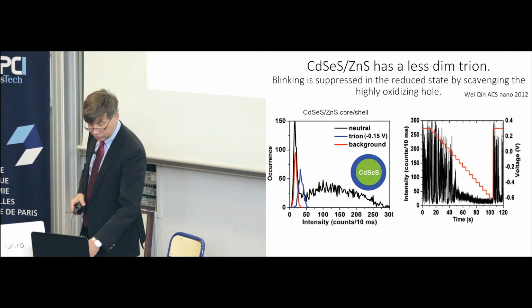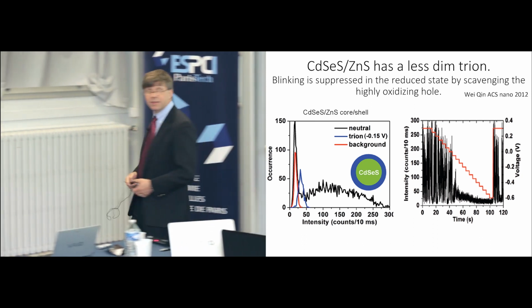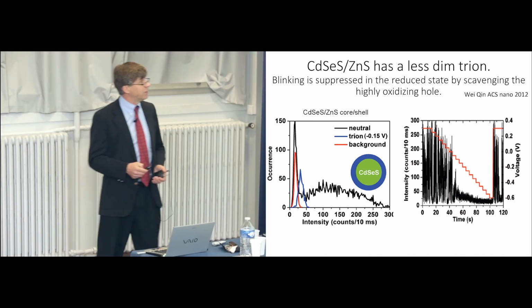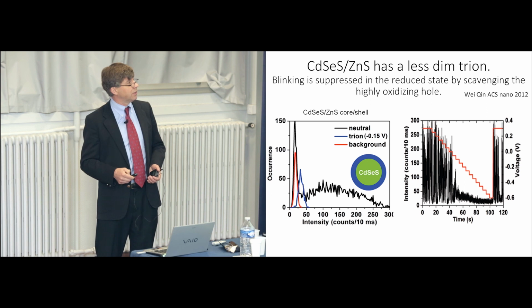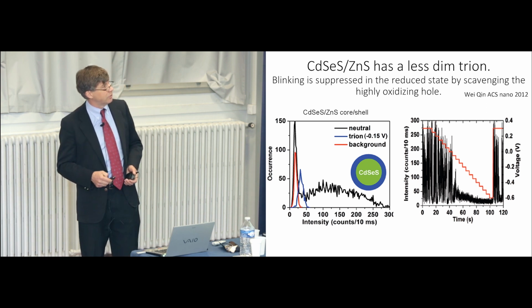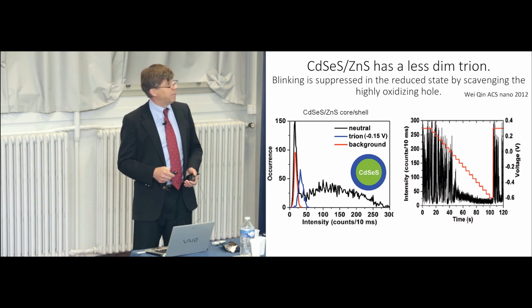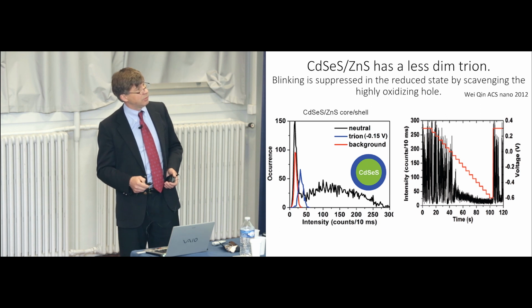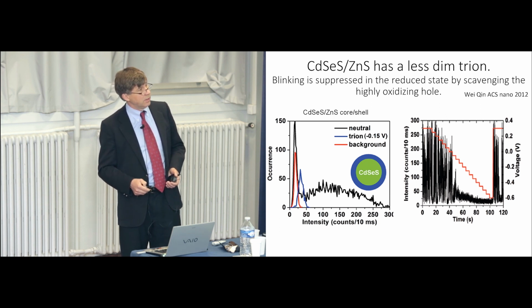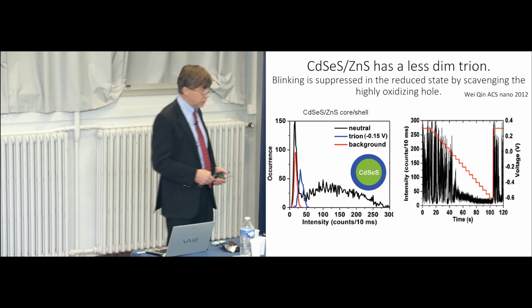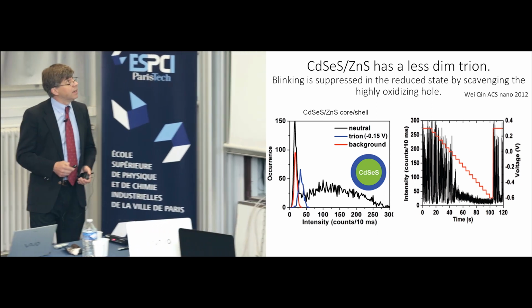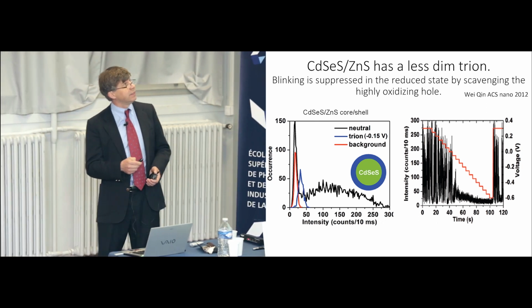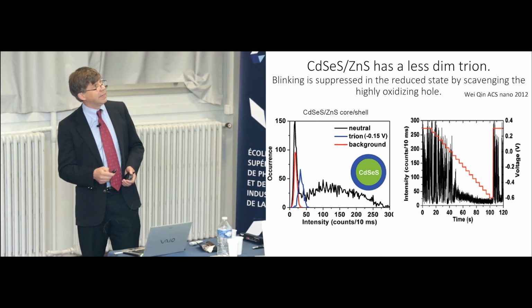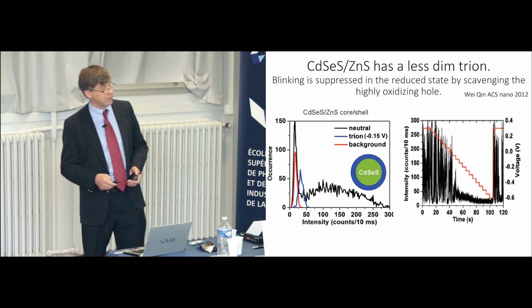So then we tried other kinds of dot. This was a cadmium selenide sulfide alloy dot, very broad, single dot, neutral emission. Not so clear why it is so broad. But clearly what was nice was that when it was charged, it was no longer blinking and it was observable. So charged dots do not blink. And I think the reason is that the blinking is suppressed by the electron, which scavenged the highly oxidizing hole. But still the challenge was to bring this up.